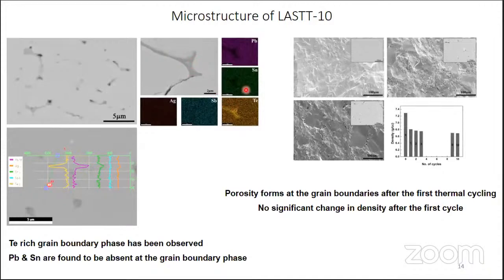This secondary phase basically consists of silver, tellurium, and antimony. It's a tellurium-rich Sb-Ag-Te kind of phase, which is appearing. Then what happens when you heat and cool multiple times or hold isothermally is that somehow this phase disappears. You see here, this is the as-prepared sample. But after you do several cycles, particularly at the grain boundary, wherever these phases were, everything becomes porosity. Something is happening.